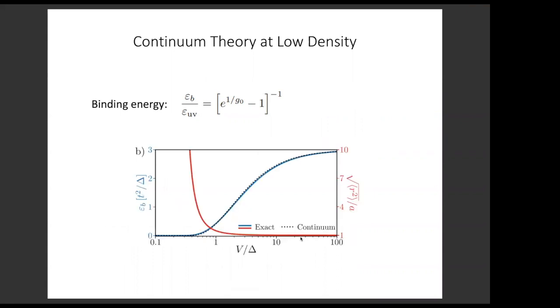So here, I'm again showing the solid line is the result from the exact lattice calculation, and the dotted line is from the continuum theory without parameters, without any adjustable parameters. Or you can say with one parameter that is fixed by the behavior at V equal infinity. And you see that perfect agreement. So this again tells us that this derivation from the lattice to the continuum theory is justified. Okay, next slide.